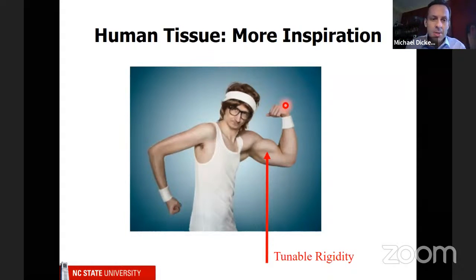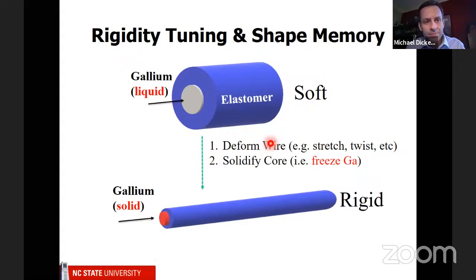So I talked about skin, but there's also muscle, which is another very interesting and tough material. But muscle, as you know, can go from being very soft to being quite stiff. And so we've used these same fibers to tune the rigidity of these stretchy materials. So this is our elastomer tube, and we put in liquid gallium, which is soft. So it's soft and stretchy. And then we can freeze it. We can freeze the wire, and that can cause it to be stiff.